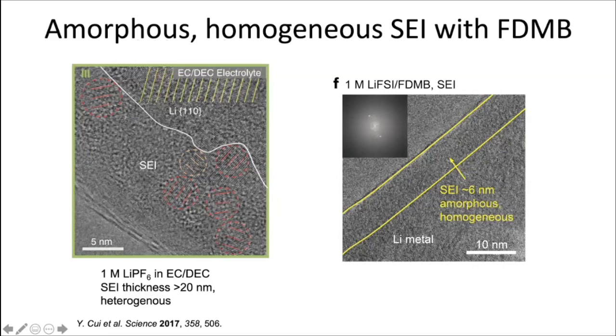And here is the cryo EM to look at the SEI interface. With the new solvent, we see a very smooth, homogeneous, and amorphous SEI that's quite thin. It's only 6 nanometers. And the left side is comparing to the traditional carbonate-based electrolyte. And also, I didn't show the XPS here, but the SEI we found is more anion-derived SEI and contains quite a lot of the fluoro groups and lithium fluoride. And this is likely due to the fact that the FSI is participating in the solvation in the lithium. There are two FSI incorporated in the solvation structure that might be incorporated into the SEI.